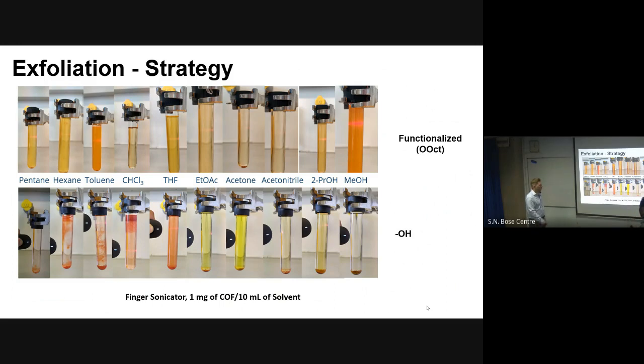It could be. I mean, we made this when we were very early in the study and didn't know how to activate it and so on, adding materials. So this dark orange is the color of the linker, and this is what we observed. Other colors could be because of the sheets you showed have the same color. And in this case, this color is typically from something which is reaching out. And I mean, those guys are not dissolving very well. You see nearly everywhere, after one night it's all precipitated, and then probably the organic molecules stay.